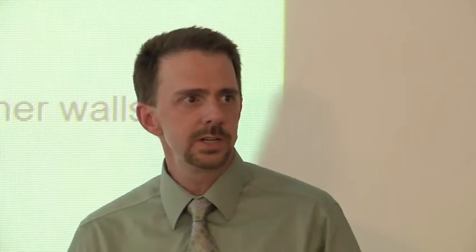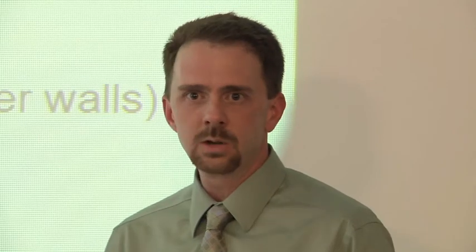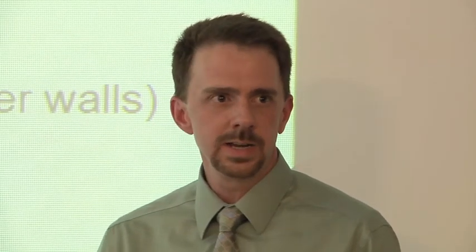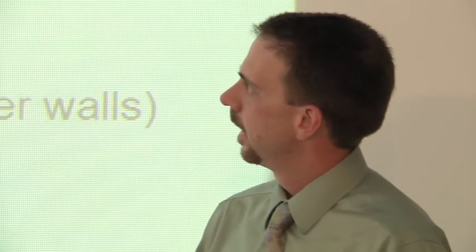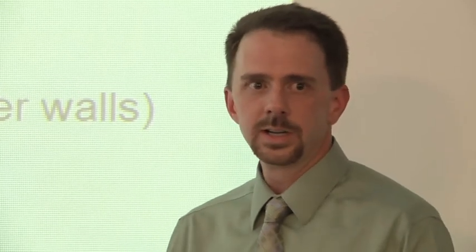So, the materials we looked at. We looked at PHD, which is that finer grain stainless steel material that's already been discussed. We also looked at something called fine grain stainless, which is just another stainless steel alloy, similar to the PHD, but just in the way it's made. It's an even finer grain structure yet than the PHD. And it gives you even more of the benefit of the flatter surface as well as the smoother aperture walls. That's the claim. And then we also looked at nickel. Nickel's kind of been the standby for a lot of manufacturers when they really have problems, nickel's the cure-all, right? So we wanted to evaluate that as well. And we looked at laser-cut nickel as well as E-fab nickel.